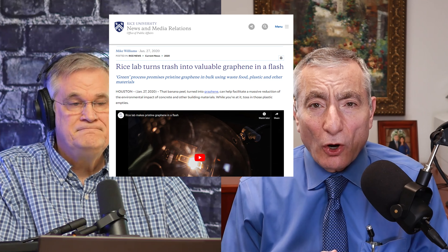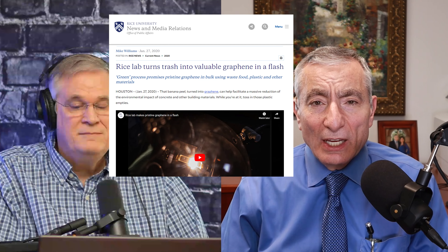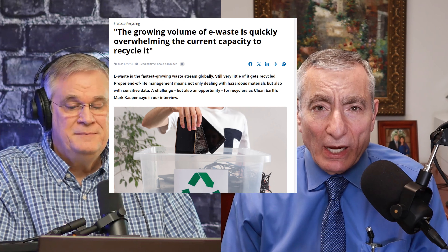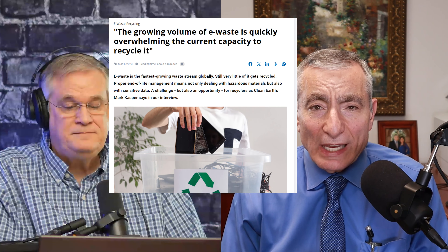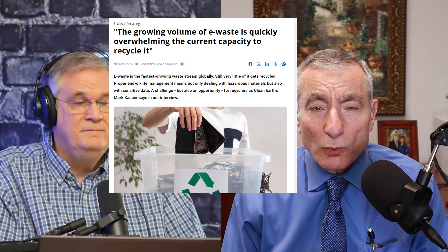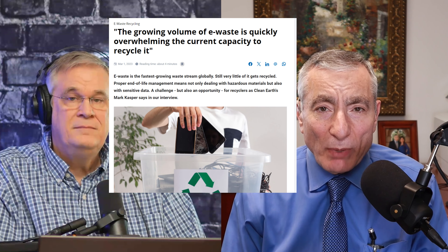We're using a similar technology to clean up the environment - putting electrodes into the ground to remove contaminants such as heavy metals, oil products, and PFAS - poly and perfluorinated alkyl substances - which are contaminating a lot of our water systems. We've learned how to degrade that. We can also take old wind turbines and old aircraft, which were normally just landfilled. Those are made of glass, carbon fiber, and plastic. When we flash those, they turn into graphene, which is a very useful material. Electronic waste is the fastest growing waste in the world - what we do with cell phones, devices, and car batteries.